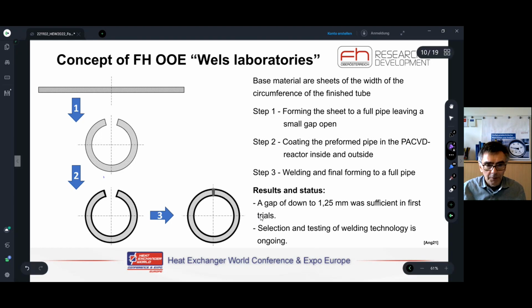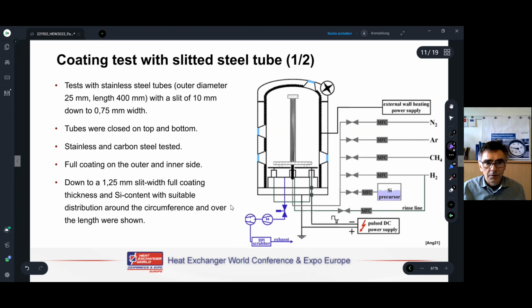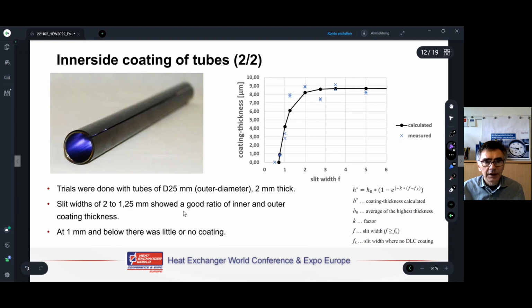The question was, how big has the gap to be? So you see here the test setup. The tube here inside with the gap closed at the top and the bottom. The gaps we tested at 10 millimeter down to 0.75, and we saw that the limit was 1.25 millimeter, where we had full sufficient coating inside, and also the silicon content was absolutely in the specification. So look here at the results.